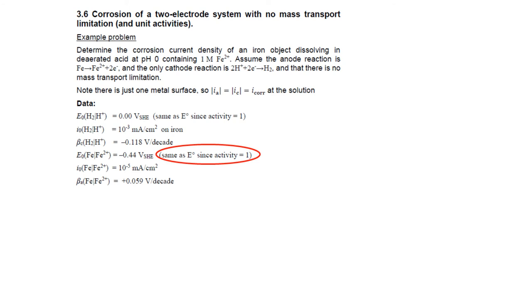It says, determine the corrosion current density of an iron object dissolving in deaerated acid at pH 0, containing 1 molar Fe2+ ions. So unit activities. Assume the anode reaction is Fe iron metal goes to Fe2+ plus 2 electrons, and the only cathode reaction is two protons, or two hydrogen ions, plus 2 electrons goes to an H2 hydrogen gas molecule. Assume there is no mass transport limitation, and the reason that we're considering the hydrogen reaction only is because the acid is deaerated, so there's no oxygen to provide an additional oxidizing agent.